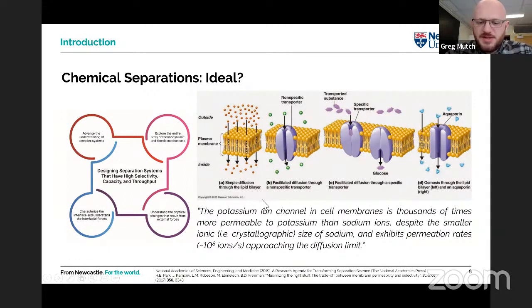And this quote, I think, basically tells us what we should be aiming for if we're separation scientists. So the potassium ion channel in a cell membrane is thousands of times more permeable to potassium than sodium, despite the smaller size of sodium, and it exhibits permeation rates approaching the diffusion limit. We can't really do any better than that. We've got great selectivity, thousands of times higher selectivity for a larger ion, but also the transport is approaching the diffusion limit. It can't go any faster. So very high selectivity, very high rates of transport. And it's all to do with these specific chemical interactions and structure, this nice, beautiful parallel pore.